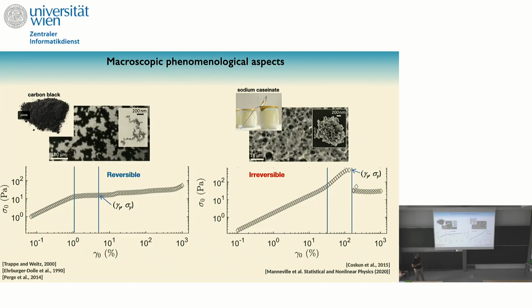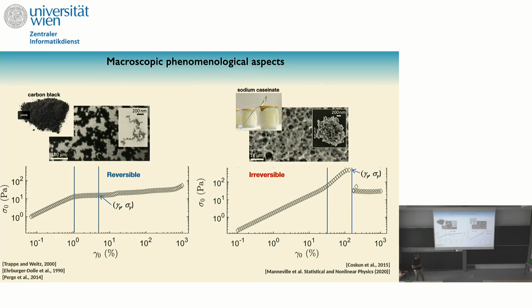On the other hand, you can have other types of systems like casein gels. This is just your yogurt. When you eat your yogurt every day, if you try to stir it, you would see that this is an irreversible process. When you stir it, when it starts to flow, there is no way to get it back unless you apply an external parameter like pH. So this is, again, a microscopic image of the network that you have, very similar to that one. You have a sparse interconnected network. This is the size of the units of these protein gels.